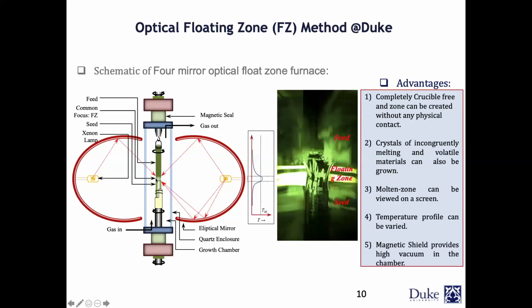This point, which we call the zone, becomes very, very hot, up to 3000 Celsius. So we can grow, I shouldn't say all kinds of materials, but a wide range of materials with different melting temperatures. The way it works is that the compound that we want to grow, we put in a ceramic rod from the top, and it's floating, so that's why it is called the floating zone image furnace.